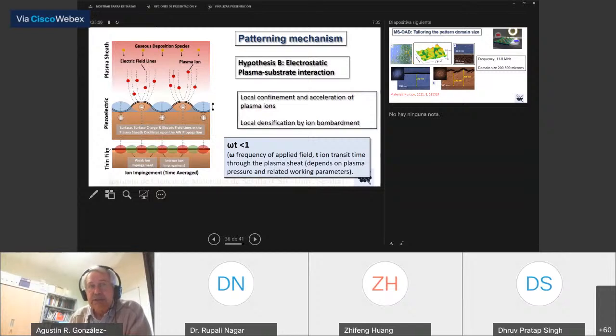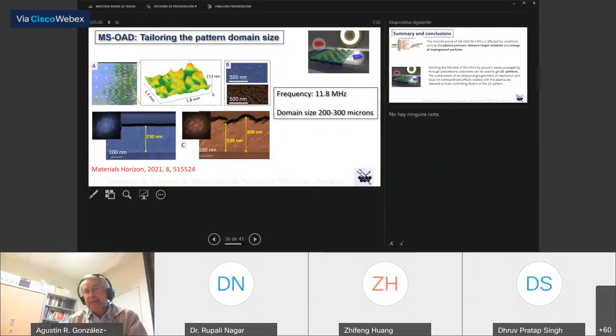Very important for this experiment is to keep the relation omega t smaller than 1, where omega is the frequency of the applied field and t is the ion transit time through the plasma sheath, which depends on the plasma pressure and thermalization degrees, on all the parameters that I have mentioned at the beginning of my talk. I have to say that the possibility of playing with acoustic waves provides also a way of tailoring the domain size. We are now working on changing the domain size, for example, by using other frequencies.